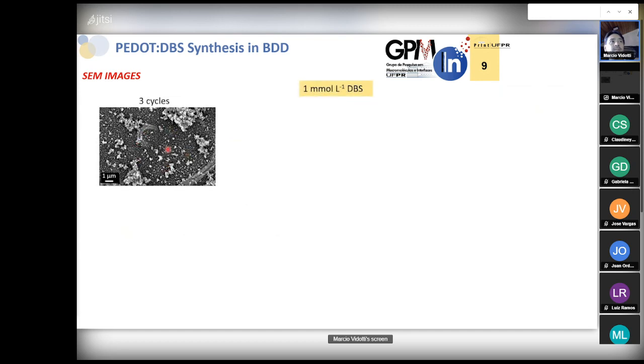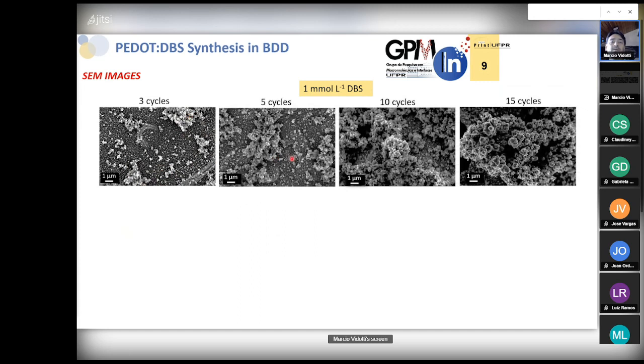So to get more information about this interface, we have done the SEM images of the modified electrodes. Here is the electrode modified for only 3 cycles of polymeric growth. We can observe these very small aggregates here, but increasing the number of cycles, clearly we can observe the increase of these agglomerates, reaching a very porous structure containing some globular structures in the nanometric region.